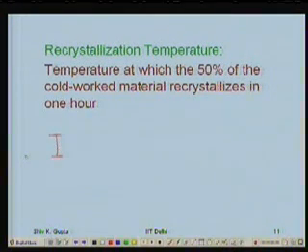Right? If you understand this, then comes the next, I define my recrystallization temperature. Those who have done the manufacturing process would have been told that recrystallization temperature is about 40% of the melting point. That's not the correct definition. The correct definition is this: the temperature at which 50% of the cold worked material recrystallizes in 1 hour. I'm specifying the time and I'm specifying the extent of the recrystallization. That means on the left hand side that I wrote the nucleation rate. Extent and time both are specified, so the rate is specified. And on the right hand side I have